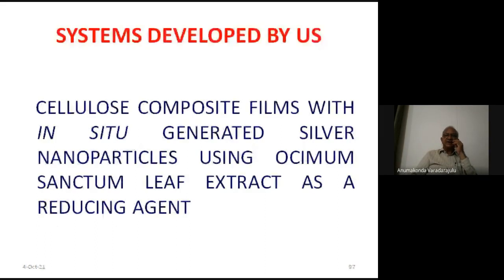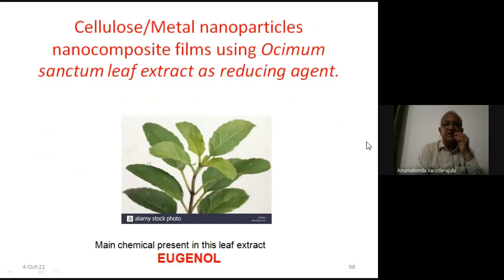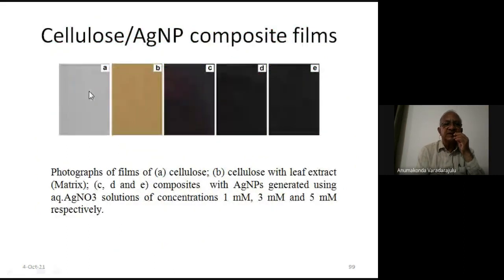So first we generated silver nanoparticles using Ocimum sanctum or the Tulsi leaf extract. This Tulsi leaf extract will be having eugenol as the main component, which is a very good bio-reducing agent. So this is the cellulose film, which is colorless, and this is a matrix along with the leaf extract, and these three are the nanocomposite films with 1 mM, 3 mM, and then 5 mM silver nitrate solution. So you can see the color change between the matrix and these nanocomposite films and so on.